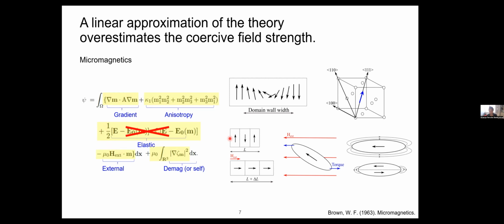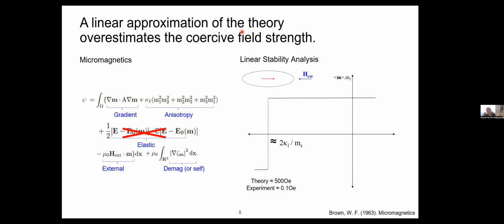And so what he did in one of his early studies was a linear stability analysis of this energy term. Essentially, what that means is you write this energy expression. You start with an ellipsoid, a large ellipsoid body. Ellipsoid is one of these geometries that minimizes your demagnetization field and is also quite elegantly incorporated in analytical calculations. And so you start with a body that's uniformly magnetized in one direction, and you apply an external field, and you identify at what value of your external field your magnetization is going to switch.